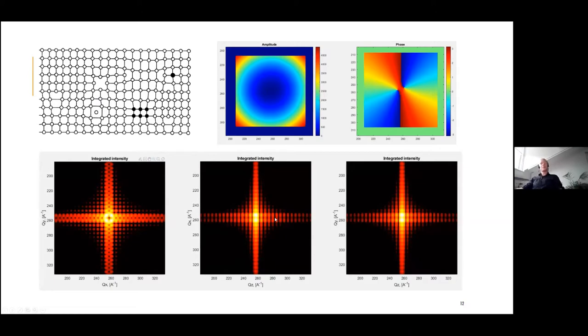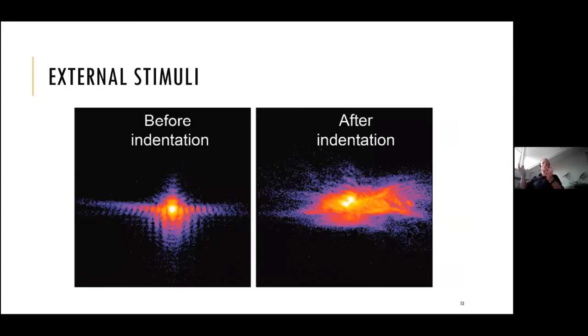It also applies to planar defects or stacking faults. The diffraction patterns start to have these certain features. And they all can intermix, so the final diffraction pattern can look very complicated. Like this one, for example, under the external stimuli. This is experimental data. If you take your crystal and shine the coherent X-rays, you see a nice fringy pattern showing a perfect symmetry. But if you start to plastically deform it, the diffraction pattern is totally away from what it was initially. And this is actually a current challenge to reconstruct this type of data.